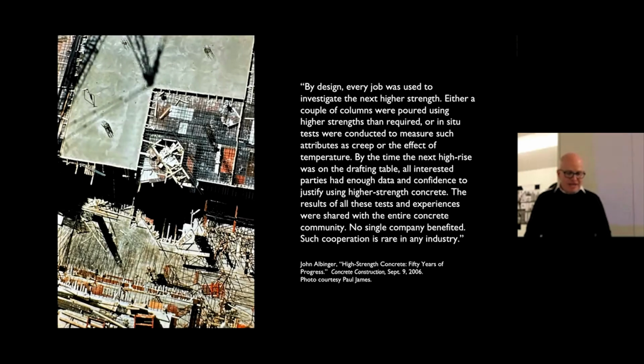And Albinger later writes that he saw that Material Services saw every job basically as a laboratory. So they would get a contract for a certain strength of concrete. They would say, we can absolutely do that. We've experimented with it. We can get 4,000, 5,000 PSI. But we also have this experimental mix that we think is like 6,500 or 7,000 PSI strength. Can we use that on your job site?